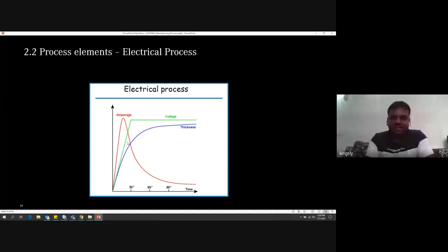So these are the process elements: the thickness and the voltage curve. As soon as you give more voltage, you can reduce the time. If you keep the time longer in the e-coat tank, then you have to reduce the voltage. Usually, industrially we get 500 volts. It depends upon the surface area how much voltage you need. We have to calculate it.